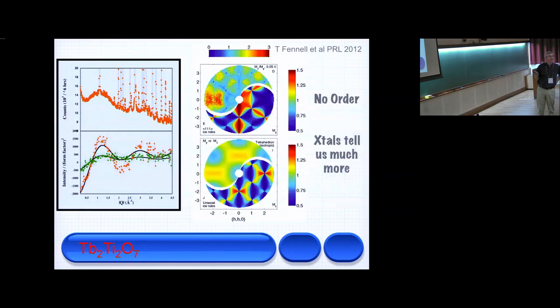So this is the raw data. And what we do is we go to, in this case, I went to 50 Kelvin, where we assume the magnetism is a paramagnet. And we take a data set and then we just do a subtraction. So that takes care of all the instrument artifacts, the crystal structure, the sample environment around you. And then I've done some binning to pull up the intensities. So like every 5 data points, average it or something like that, and you get this. And in this case, I've actually gone through with the form factors so that we can start to model it a bit more.